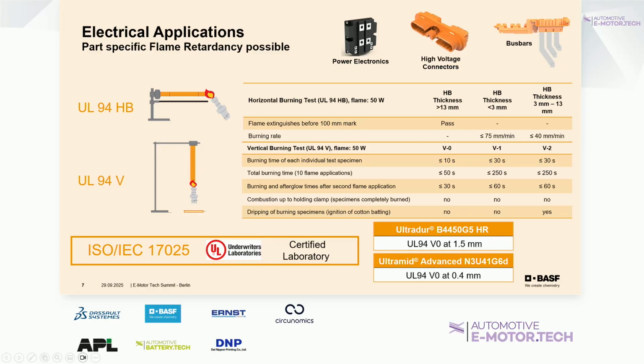What's important to mention here is that we see these tests as quite a common requirement in the E&E industry. But what we do here is we do the test completely in-house. We have a certified laboratory in Ludwigshafen at BASF. We produce the test specimens and directly run the tests in-house, and they are, as I said, certified. So we see a huge demand for these tests, but we are able to cover that with high speed.